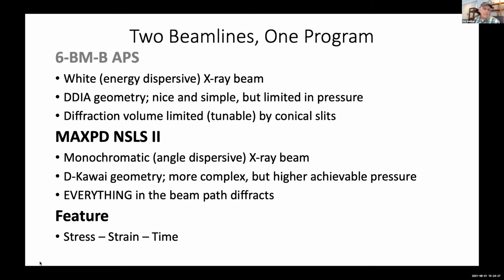With the APS system having energy dispersive, we built a detector, a conical slit, we call it, which allows us to have multiple detections all at the same 2 theta angle, but around the point of the detector. The APS system has a 200-ton press and is fairly limited in pressure. The Kawai system has a 1,000-ton press, and so gives higher pressures, but with the white beam and a 2D detector, everything in the beam contributes to the diffraction.